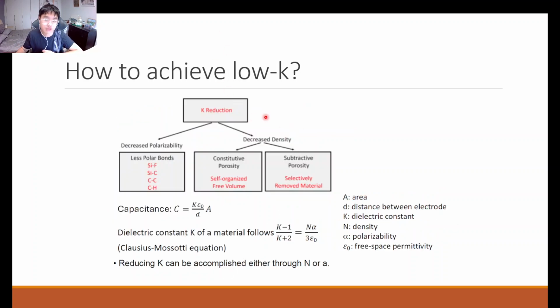And so how do we achieve a low-K dielectric? So the dielectric constant of a material can be decreased in two ways. So remember that the dielectric behavior of a material arises from the polarization of the chemical bonds present in a dielectric material. So it then logically follows that if we have a decreased polarizability of the chemical bonds in a dielectric material, we can achieve a lower dielectric constant value. And so we can use less polarizable bonds, right? For example, your non-polar bonds like C-C and C-H are less polarizable.